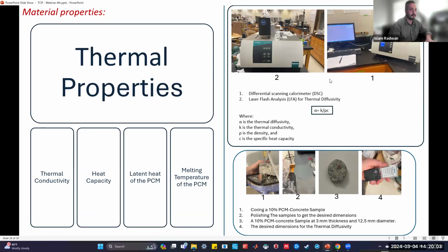As we can see here, we do have two devices. The first one is the differential scanning calorimeter, the DSC, and this device is used for measuring the specific heat capacity. And the second one is the laser flash analysis, which is used for the diffusivity. And if we recall the equation, the diffusivity equals the thermal conductivity over the density times the heat capacity. So if we can measure the specific heat capacity and the diffusivity, we can get the thermal conductivity.